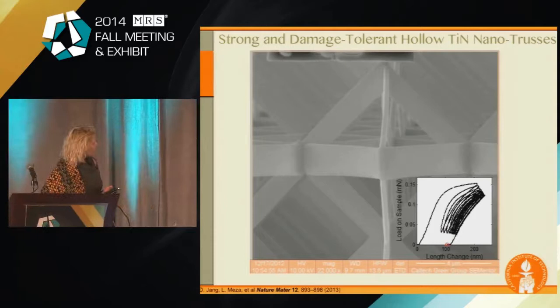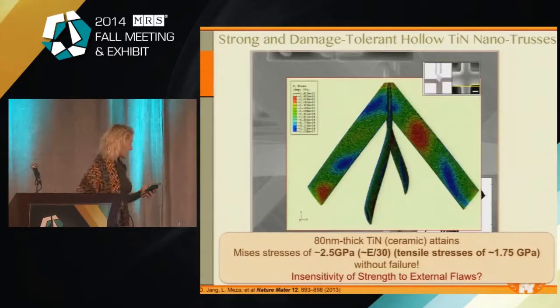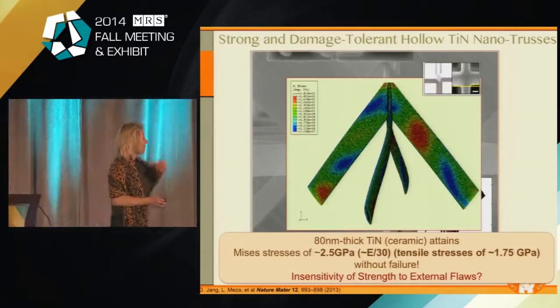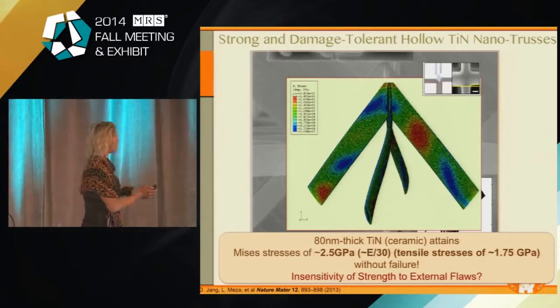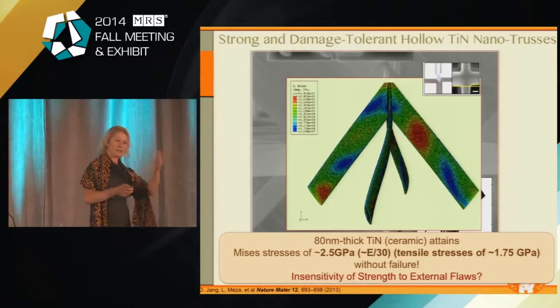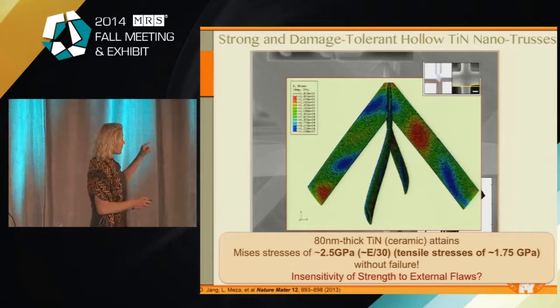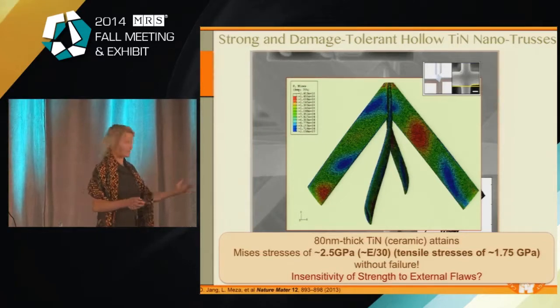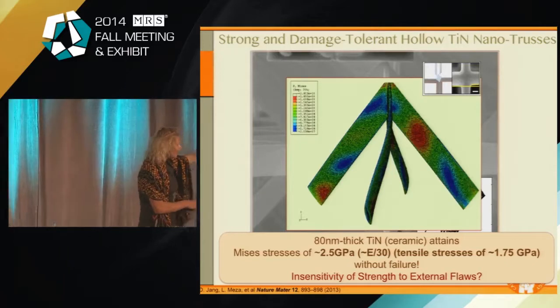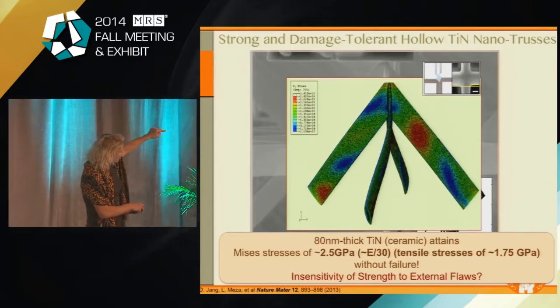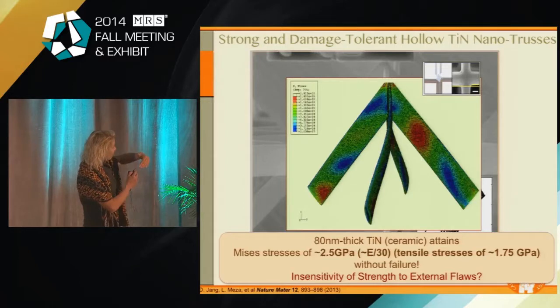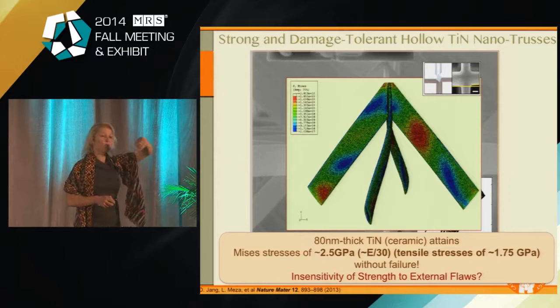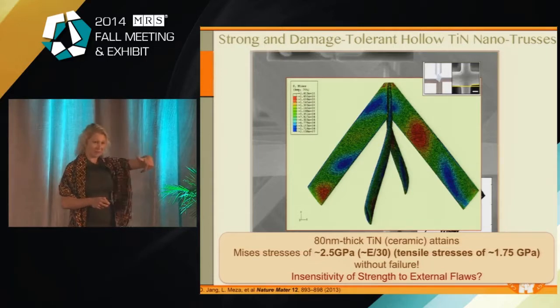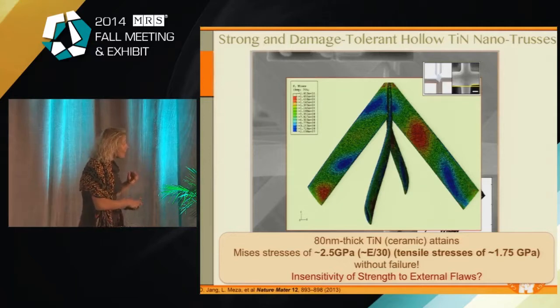Now, since they're deflecting, we couldn't calculate the stresses very precisely, so we had to do some FEM modeling to understand the stress and strain distribution within these beams. They're also elliptical, so there's clearly a bending moment. So it turns out that the answer to one of the questions is very simple. Why are they deflecting? Turns out that these structures are slightly imperfect. If you look at it from the top, you'll see that there's a little bit of an offset between the diametrically opposite beams. Because of this offset, when you start pushing on it, it generates a torque. And when there's a torque, there's going to be a bending moment on these, right?